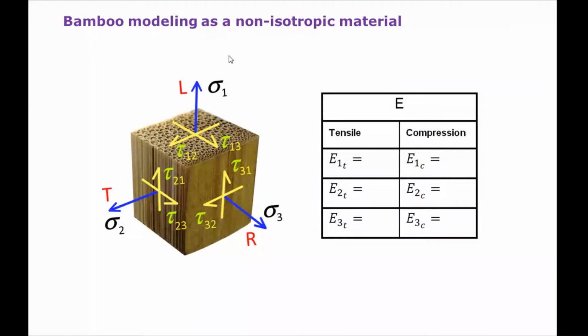If you want to model bamboo with, for example, software like Abaqus or ANSYS, you should consider that bamboo is not an isotropic material. It's a non-isotropic material. It means that you should consider different Poisson ratios, and you have different moduli of elasticity in each direction: longitudinal, tangential, and radial. You have different Young's moduli. Also, it's important to notice that in tension and compression, the modulus of elasticity is different. It's interesting. It's very difficult to model bamboo with software considering all of these aspects.